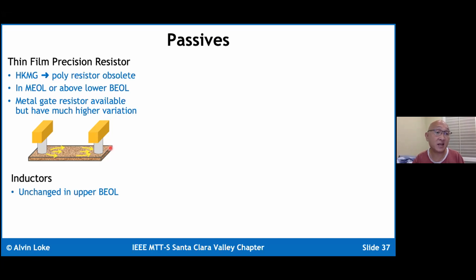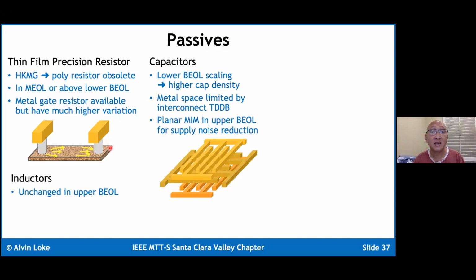Inductors have largely remained unchanged in the upper back end of line. Capacitors, you are getting a little bit of higher capacitance density due to the lower back end of line having a tighter metal pitch. But what I'm seeing more and more of is the metal space is increasingly the limiter in terms of interconnect TDDB reliability. Basically, if you can't keep your metal lines really tightly spaced, you're not going to get a lot of capacitance density. So that's something to keep in mind.